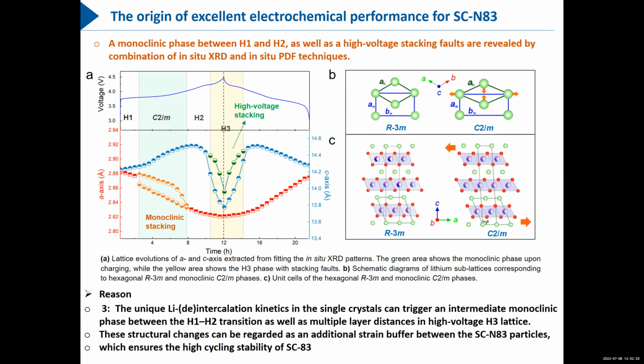Is it due to a too small particle size, so that your diffraction may not have enough resolution to identify the different lattice parameters? You know what I mean? For a large single crystal, you can probably determine the lattice parameter more precisely, and for smaller sizes, due to strain or other effects, it's not easy to differentiate this difference in the lattice parameter. No, I don't think so, because this is a high resolution and high power synchrotron technique. So it won't miss any tiny structure change in the characterization.